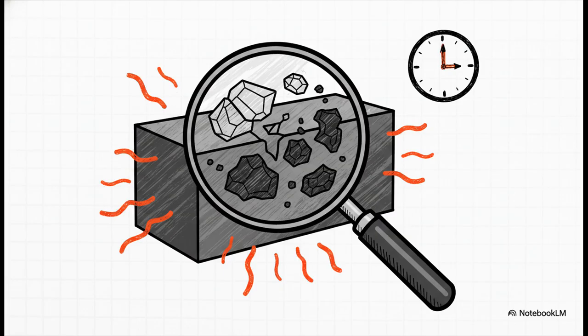If certain carbon steels are subjected to extreme heat for long periods of time in the field, say sitting between 450 and 600 degrees Celsius, they undergo this weird metallurgical change called graphitization. The structural carbides in the steel literally break down into small, weak patches of graphite and iron. So yeah, heat remains a highly destructive force long, long after the casting is solid.